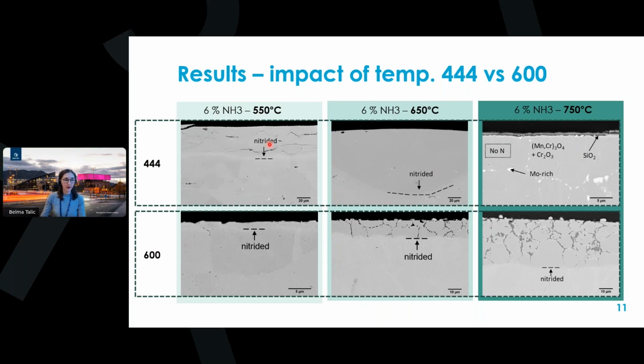For 444, we see that at 550 degrees, there's an even layer that has become nitrated. We have some cracking starting to occur in the nitrated zone. When we increase the temperature, we see an increased depth of nitridation, but the content of nitrogen in the alloy has been slightly decreased, and we don't see any cracking anymore. And then when we move to 750 degrees, for this alloy, we don't see any nitrogen anymore. Instead, we see that a surface scale has formed on the top of the alloy.